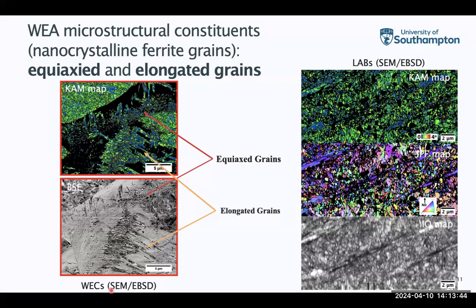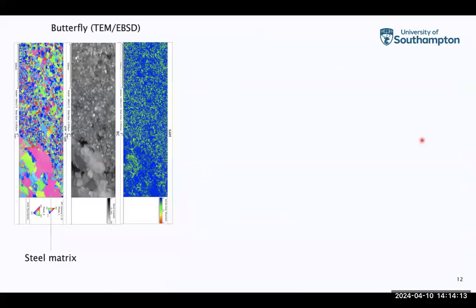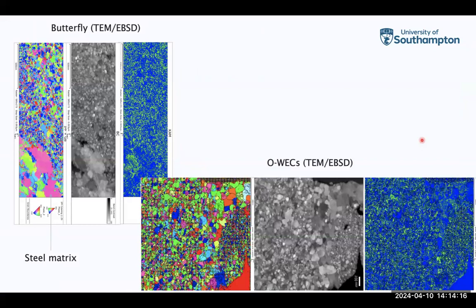So this is for the white-etching crack. For one of the white-etching cracks, you can see the 2 different types of nanograins. And these are for one of the low-angle band structures. You can see they also have the equiaxed grains and elongated grains. So in both structures, you can see the 2 different types of grains in their microstructure. For the butterflies and the orientated white-etching cracks, we found that they only have equiaxed grains at different sizes, and we rarely see elongated grains in them. So they are slightly different from the white-etching cracks and the white-etching bands.